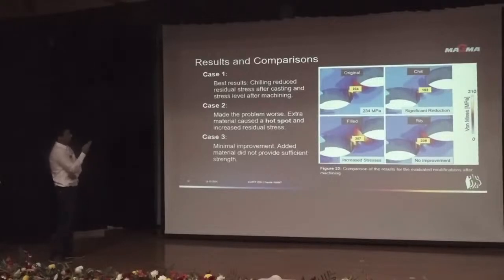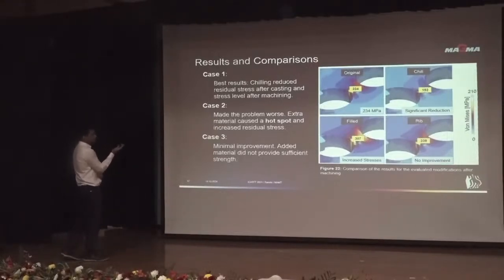This was the original design, where we were getting 234 MPa of stress at that region. But after putting a chill in the casting, it was reduced to 152. When we filled it and machined it later, it didn't help much, and when we added ribs, there was no improvement either. So the best case was putting a chill between those holes.